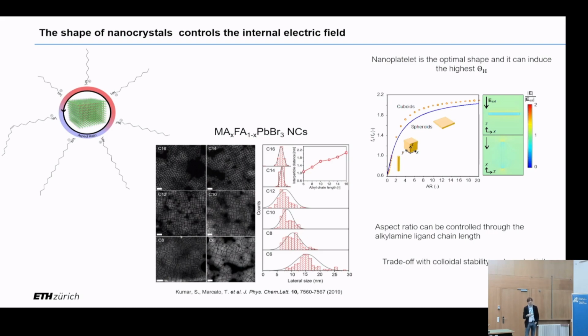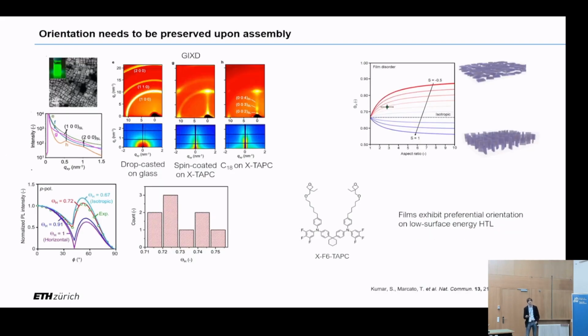So we synthesized them, and the next problem we had to face is order assembly. We had our individual nanocrystals, which we believed had anisotropic emission, but at the beginning, if you just take this solution and drop cast on glass, we always measured by angle-dependent photoluminescence just an isotropic emission. Of course, because you can see here is the predicted anisotropy of the film, depending.